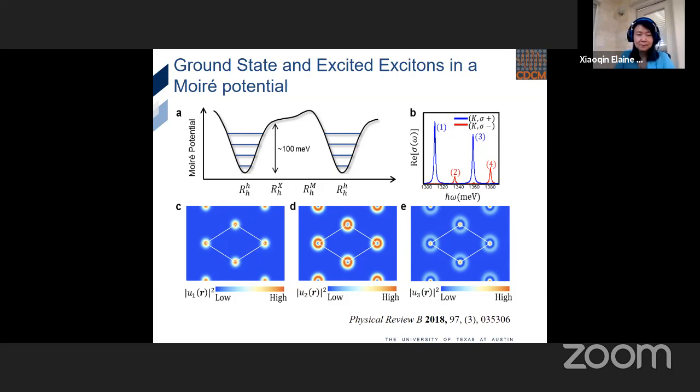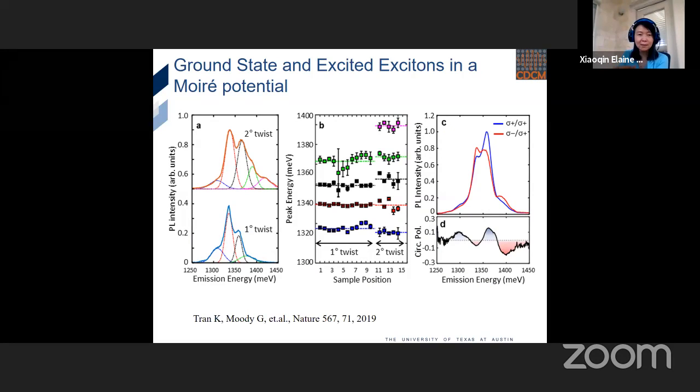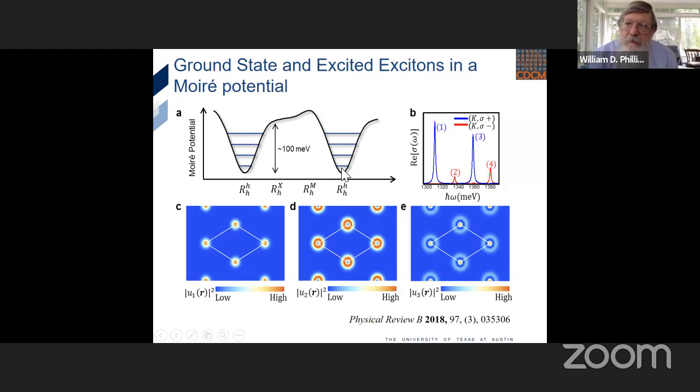So what I want to know is whether the fact that in the square well, as I go to higher energies, I get bigger spacings, whereas in a sinusoidal well, as I go to higher energies, I get smaller spacings, has any important effect, or whether it's just the first two levels that you're worried about anyway. Right. So again, this depends on what material combination I choose and the specific twist angle. In our measured cases for MoS2 and WSe2 for the near 1 degree sample, when we fit the energy spacing, they're roughly equal. Therefore we used this parabolic model.